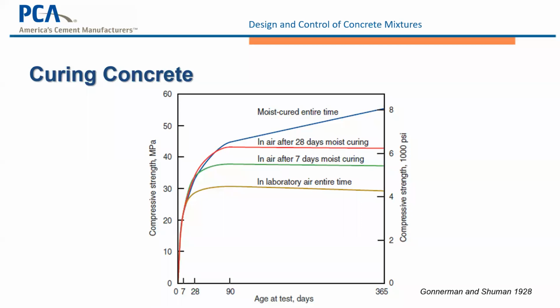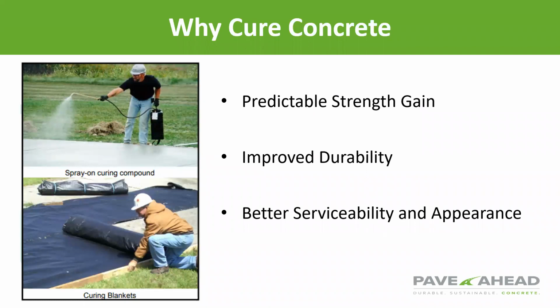That was 28-day strength. So you can see in this particular case, the concrete strength at 28 days was 6,000 psi compressive strength. If it wasn't cured or cured improperly, that were much less than what that pavement were designed for in the first place. And it also shows that if you moist cure the concrete, you get a higher strength than it was designed for at a 28-day stretch. Concrete curing really gives you predictable strength, pavement durability, and overall appearance on your pavement surface.